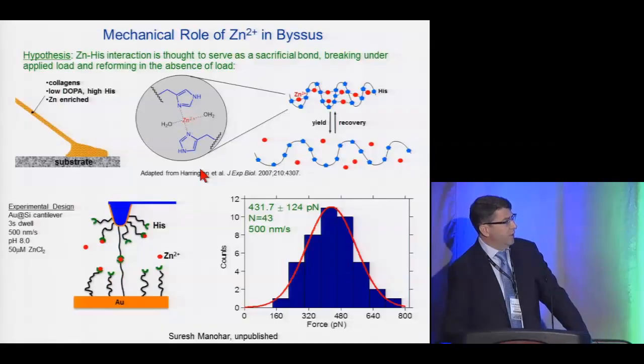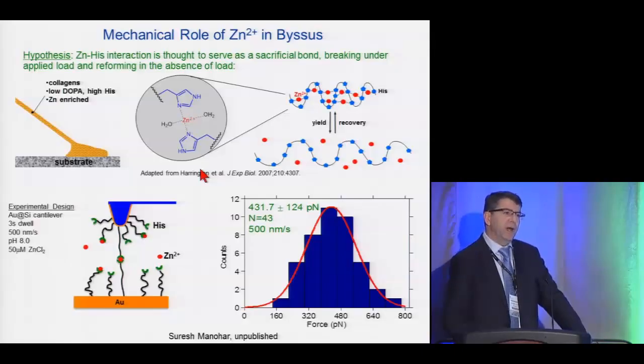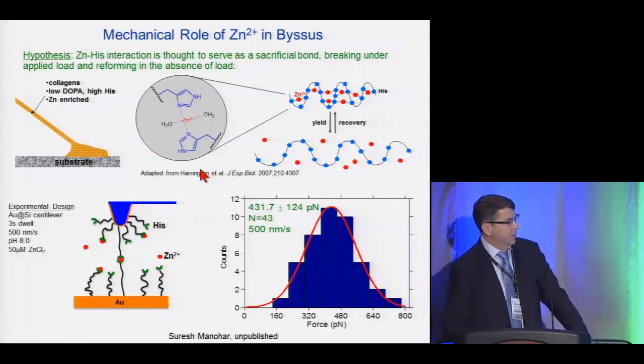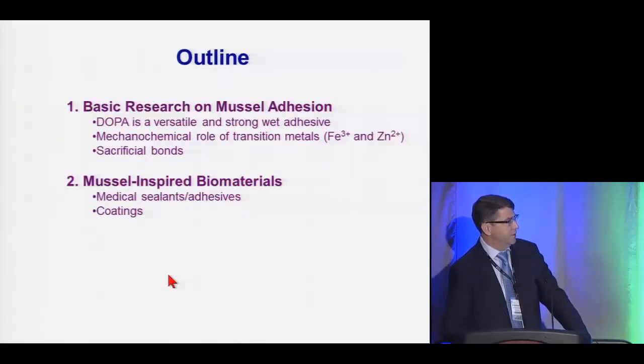And one of the things that has driven this hypothesis in our study is that if you pull on these threads, you can pull them past their plastic deformation limit, and then they self-heal over a period of a few hours to recover their elastic properties. So it's a very interesting system, and we believe that it's the sacrificial rupture and then reformation of these coordination bonds that gives rise to the recovery, self-healing, if you want to call it that, of the tissue.